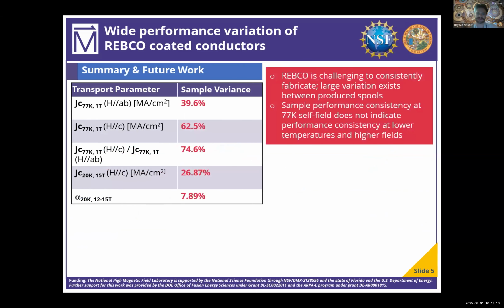So what we learned, we found that there is a lot of variation between spools of REBCO tapes, even if they are produced to the same specifications, and that REBCO is challenging to consistently make. There is a lot of variation, and sample performance at 77 Kelvin and self-field does not indicate homogeneity at working conditions, so at 20 Kelvin or 20 Tesla.